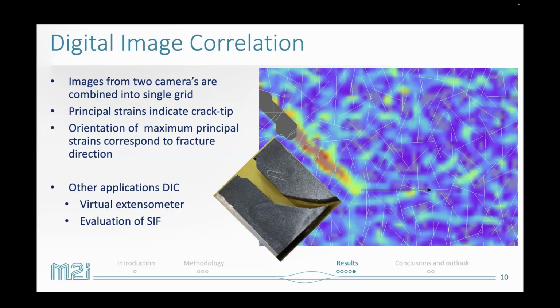Other applications for the digital image correlation are calculating stress intensity factors, for example, or using it as a virtual extensometer, because the normal extensometer is only able to calculate crack opening displacements, because it's attached to the specimen itself, and the crack sliding displacements are not captured by that. But using the DIC, we can decouple these.